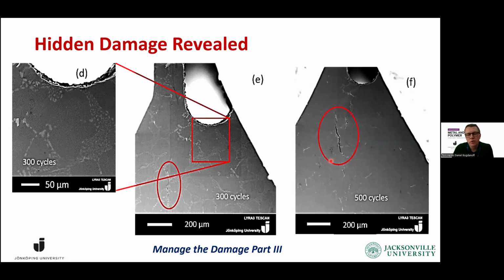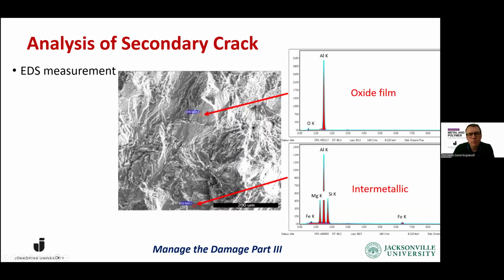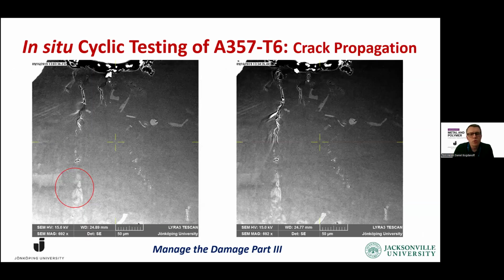So here we see that we have new crack initiation spots that will coalesce with others, and that will be the fatigue. And we confirmed that this was an oxide film in this crack propagation in this area by using EDS on the surface, in this case, in this paper that we worked with. I will show you a little bit further, more data about this.